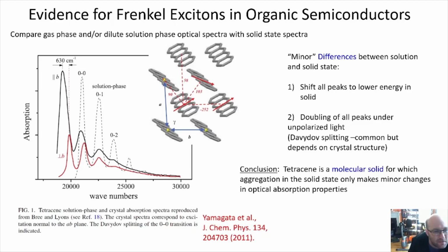And then finally, the fact that there's a series of peaks, not just one absorption peak, is also important, that we'll come to again in just a few slides. So the differences are minor, but I guess what I want to say about this series of peaks is that it is actually further evidence that this is a fundamentally molecular exciton, right? That's the vibronic progression that tells us we're really looking at something that is associated with a very specific molecular structure that hasn't changed much in going from dilute solution to condensed solid state.